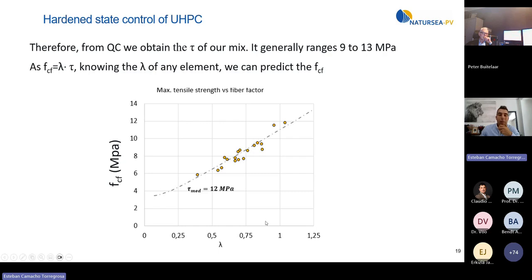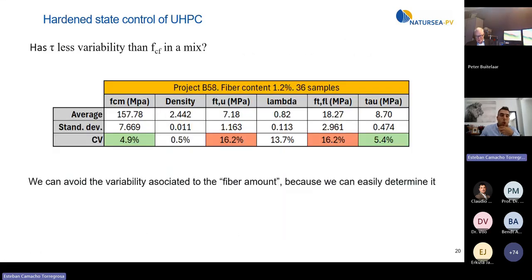This is a plot of a population, a group of a sample of beams with the same material, showing how there is a clear correlation between the post-cracking strength and the fiber efficiency factor. And this slope is the bonding strength, in this case, 12 megapascals. So now comes the question, is it better to design and to obtain the bonding strength than working directly with the post-cracking tensile strength?